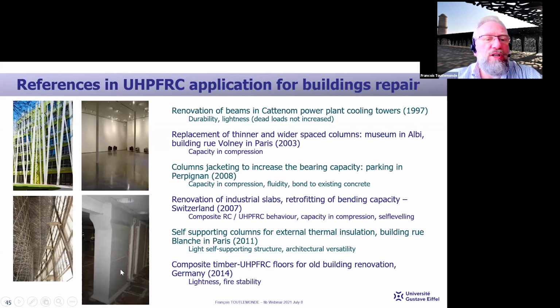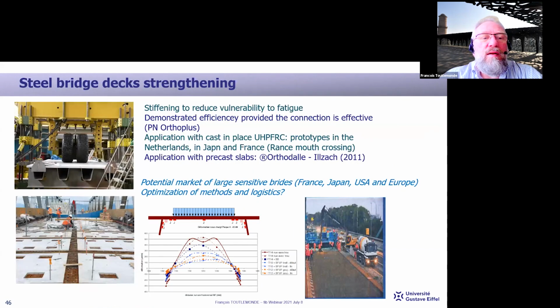Here it's in a parking because the building had to be increased in height by several additional stories. I mentioned the steel bridge deck strengthening because we have a generic issue with orthotropic deck bridges, at least in Europe and Northern Europe, because these structures are very much sensitive to fatigue, especially at this junction between the troughs and the plate.